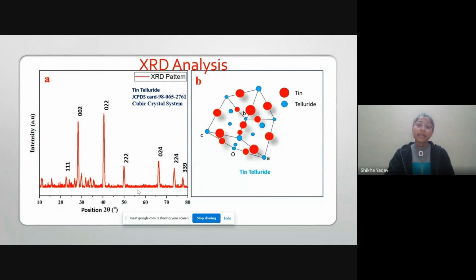This was the XRD pattern that I obtained using my XRD data. These were the diffraction peaks that I observed, and they matched with the JCPDS card number shown. The pattern displayed on the screen is the smoothed data. Actually, at 28 degrees I got a broad peak, and that broad peak means that it is a semi-amorphous material that we obtained.